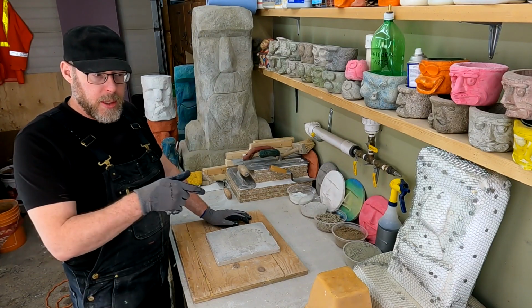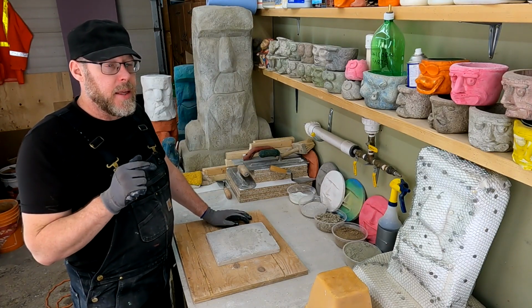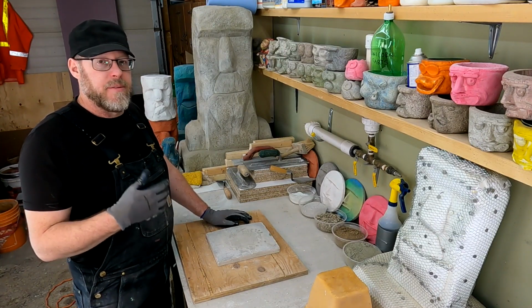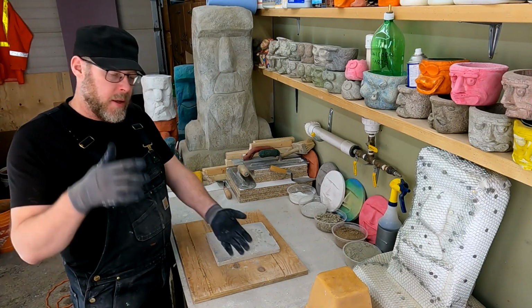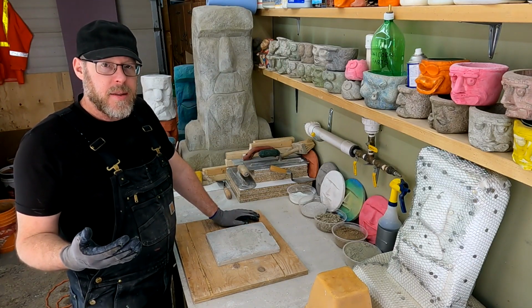If I wanted to drill a hole and take a piece of rebar and put it in that hole and have it stay in there, I could use an epoxy product, but I could also use non-shrink grout. I prefer the non-shrink grout method for something like that because with the epoxy, moisture is a concern. It's hard to get the water out of an 18-inch deep hole, things like that. Then there's dust, which is also a concern.